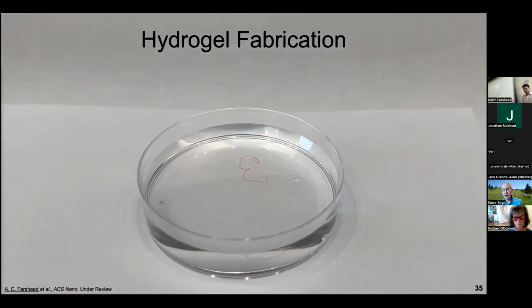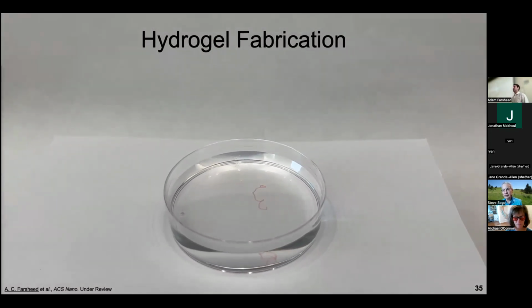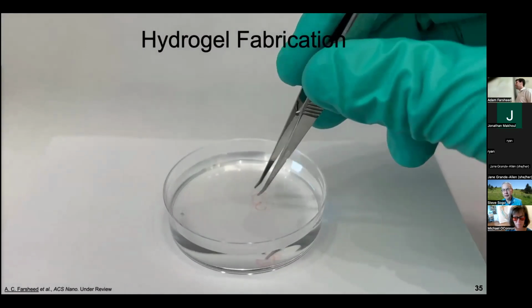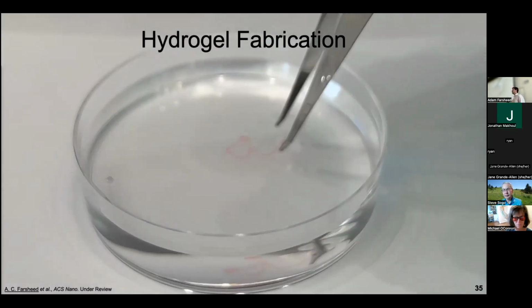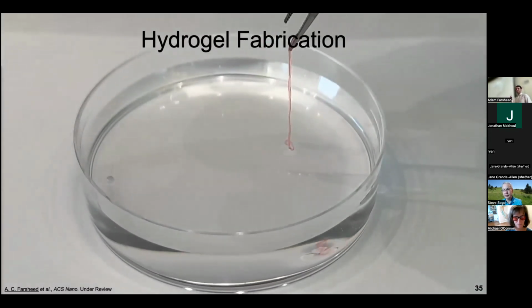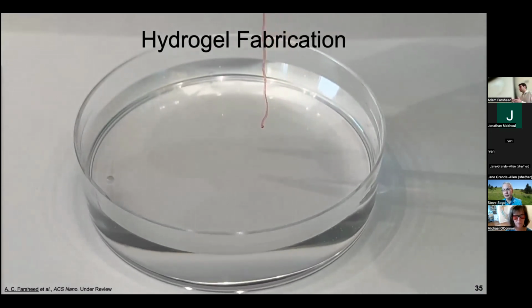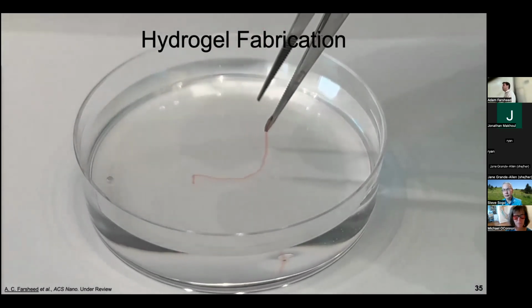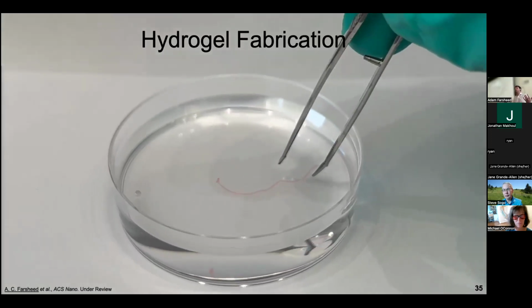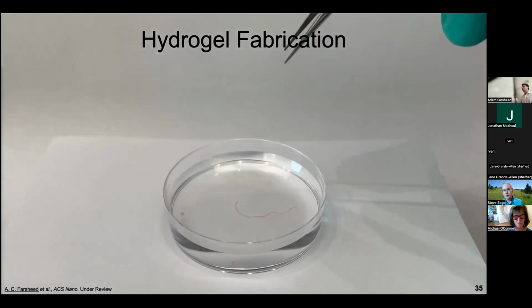And what was actually most exciting about this work, because we didn't really know any of this stuff yet, is that we could actually pull these little hydrogel noodles out of solution. Now, why this was so surprising for us is because we're, again, working with a supramolecular self-assembling system. And so within all of this, there are no covalent bonds holding this noodle together.